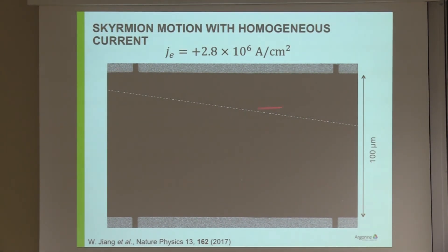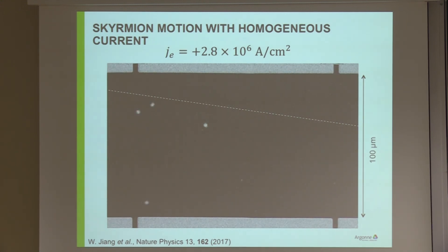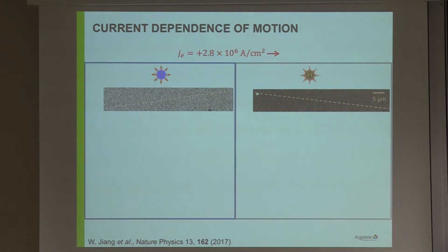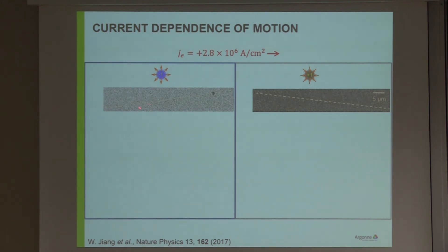The next step was to look at a homogeneous wire — the skyrmions are created out of the field of view by a metal contact. We picked a field condition where we didn't have too many skyrmions but enough, and we saw that they moved along a single line in the same direction. If we flip the field direction, the skyrmion moves upward rather than downward, which is evidence of a change in topological charge — flipping the topology gives the opposite Hall angle.